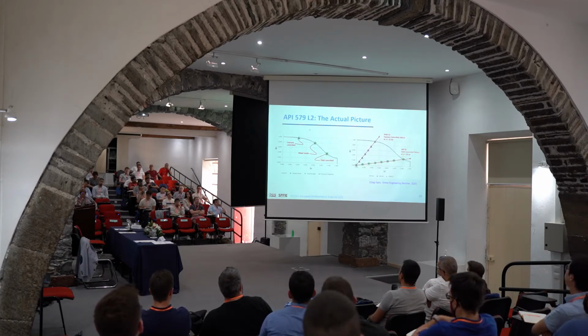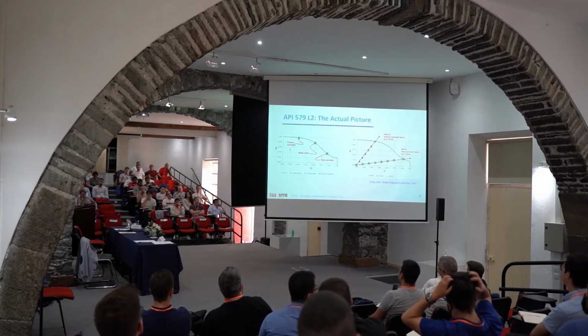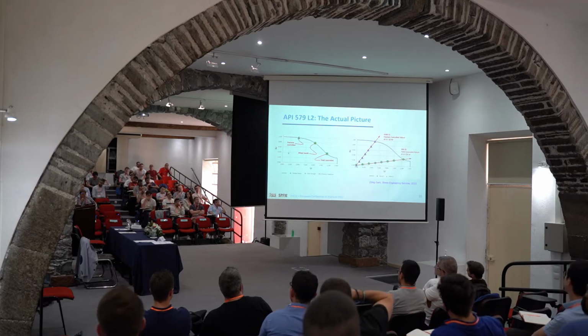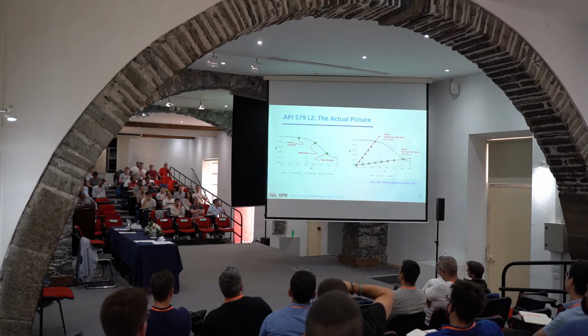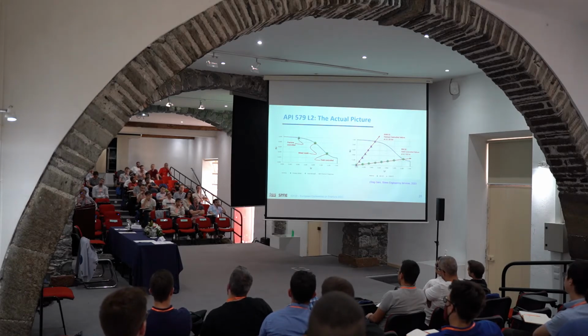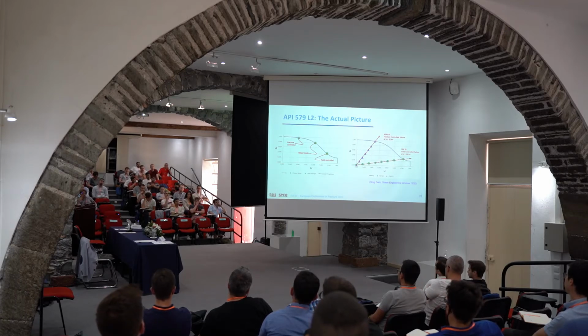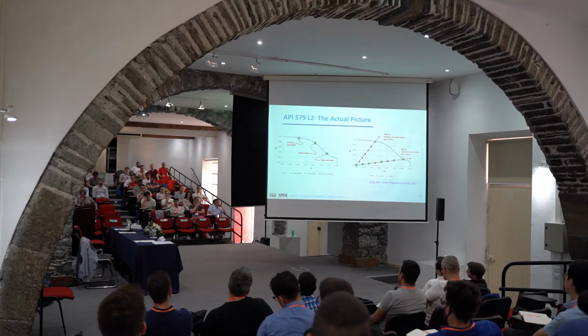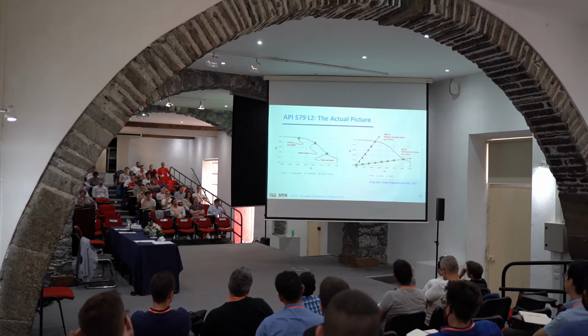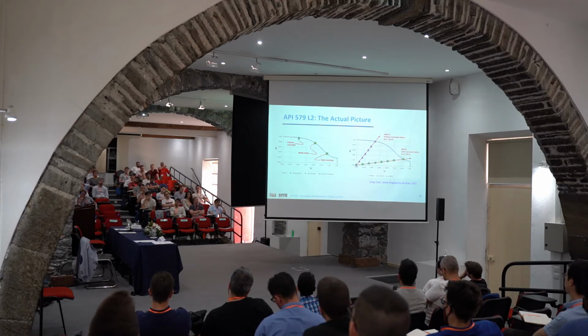Okay, that's another way of showing this. As you can imagine, if you are on this side of the curve, that means the material is brittle, because your Kr is close to 1. And if you are on this side of the curve, here, that means your material has very high toughness. So the failure is controlled by yielding, not by fracture.